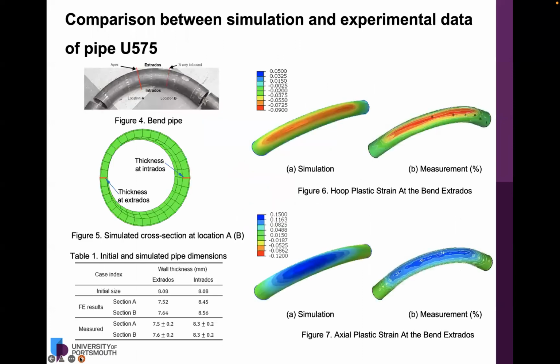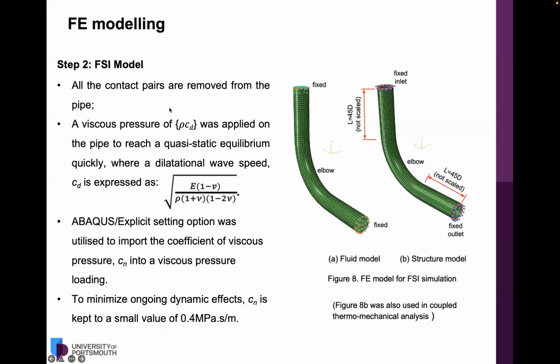Once we've done the model, we run the simulations, and our results from the simulations were compared with the measurements results from the experimentations done by Kajespur and Yetisir. In short, we found that they are pretty much in agreement, so the simulation and the measurement results are pretty much in agreement. So this gives us a confidence to move to the next stage or step, which is the fluid structure interaction modeling.